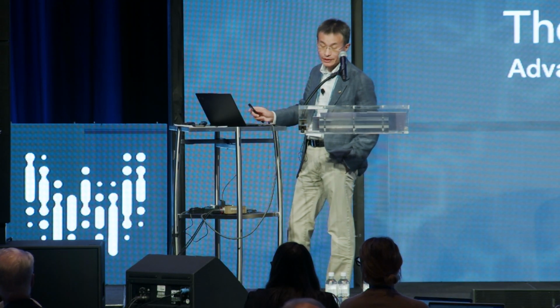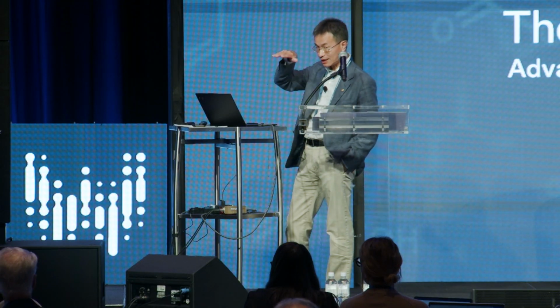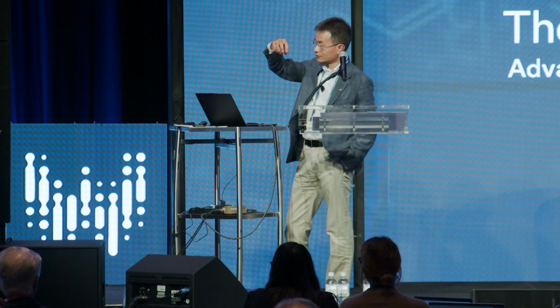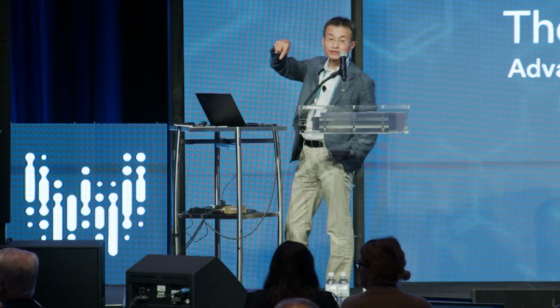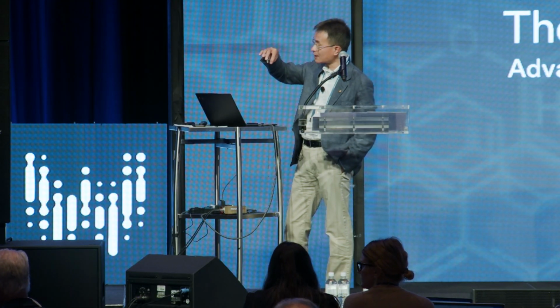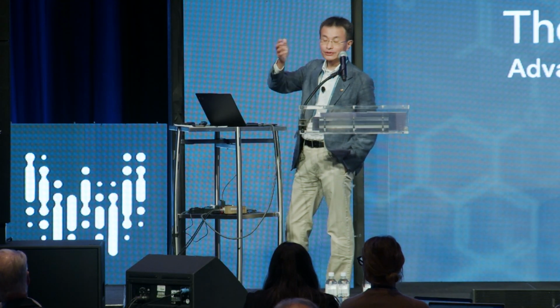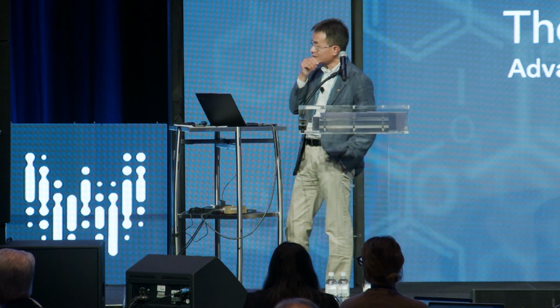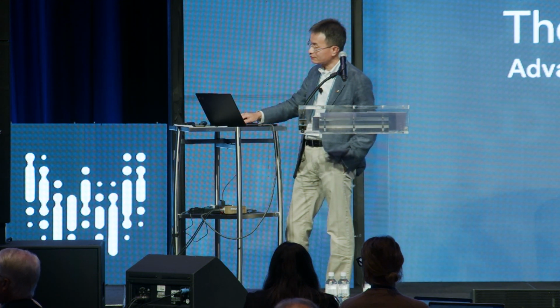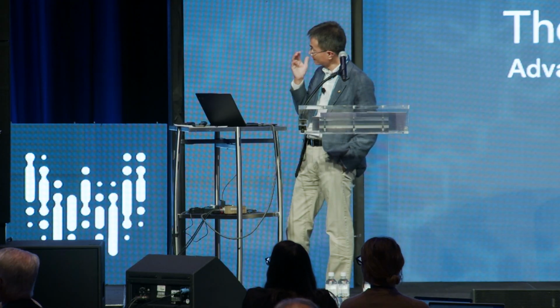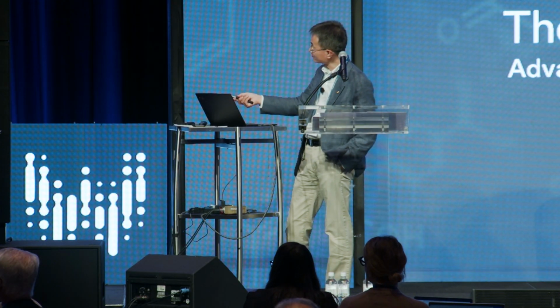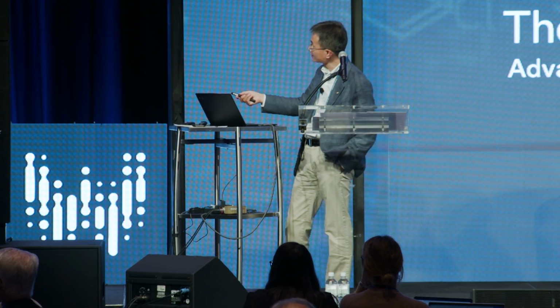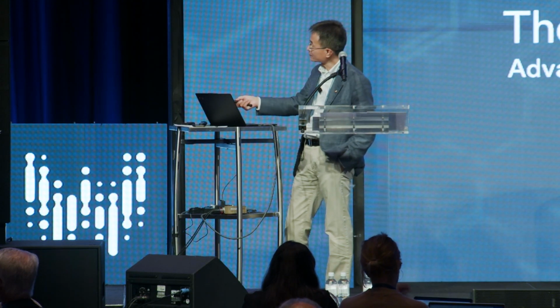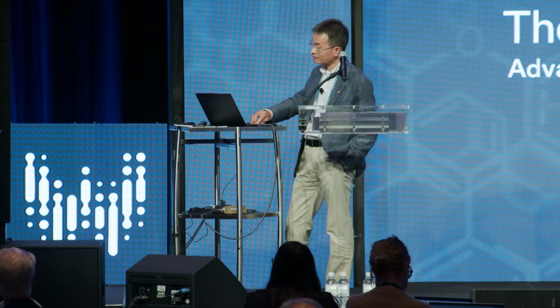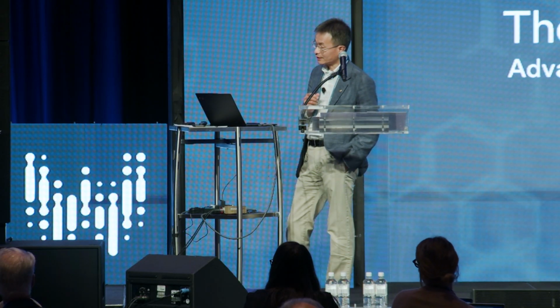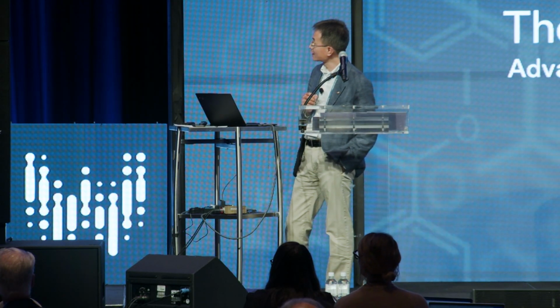They are single domain, okay? And their end facet is hexagonal, okay, because in this case, zinc oxide or gallium nitride have the wurtzite structure. So typically they are hexagonal. Cross-section is 100 nanometers. And of course, initially when we look at these lasing phenomena here, there are two panels of optical spectra under different optical pumping, and this is the emission speckle. You can see that's typical behavior of coherent irradiation from the end facet of these nanowires.